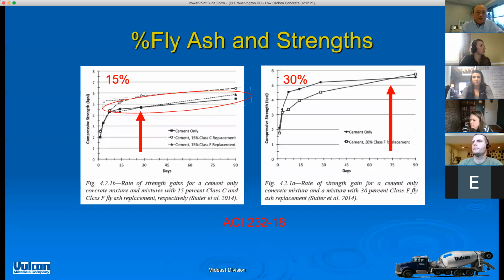So this is another comparison of the percent of fly ash and its impact on strength. On the curve on the left-hand side with 15% fly ash, you can see that the fly ash starts off lagging the reference, the 100% Portland mix. But by the time 28 days comes around, it actually crosses over, meaning that fly ash starts to generate more strength as you go past 28 days. Conversely, if you look at a 30% fly ash mix, the crossover doesn't happen until about 70, close to 75 days later. So that just gives you an idea. If you recall from the strength development curve with slag, the crossover happened much sooner. So, just the behavior of different materials. Next slide, please.